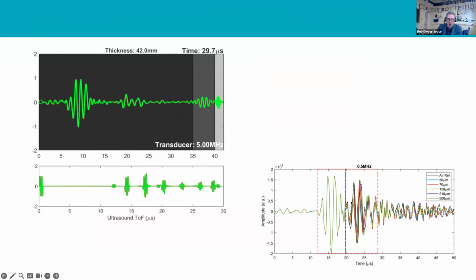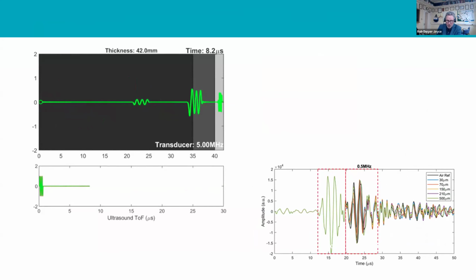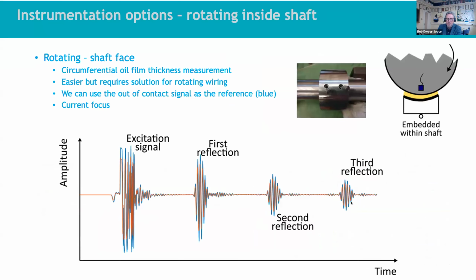So at the moment, we're not working on this. We have done some work on this, but we've paused that. And we're working on another approach to doing this, which is going from the shaft side. So what we do now is we put a sensor in the shaft, which means a hollow shaft, somehow getting the wires out, running it through slip rings, and then recording as the sensor passes into the oil film thickness and out again.